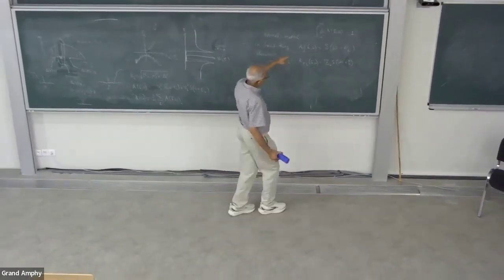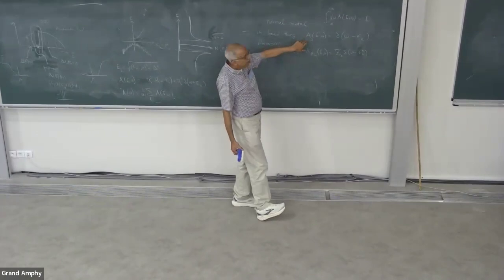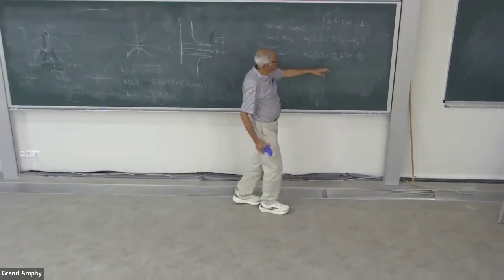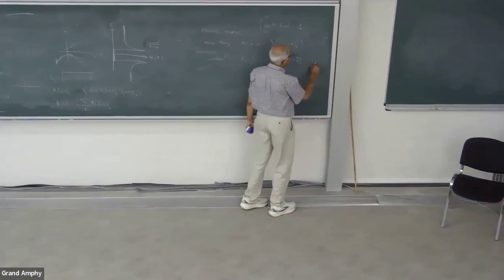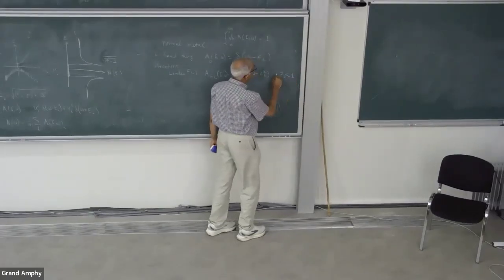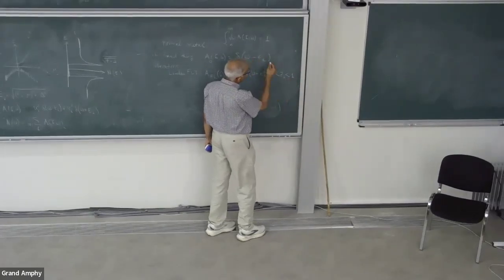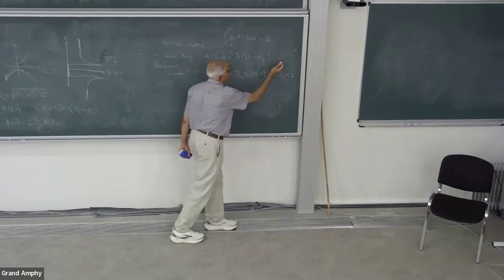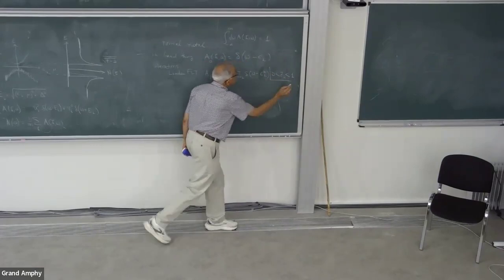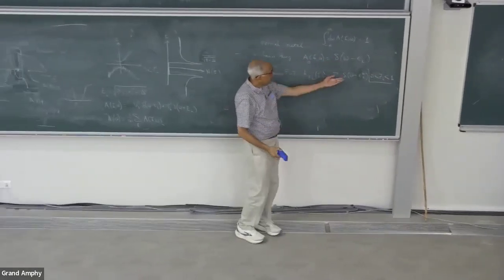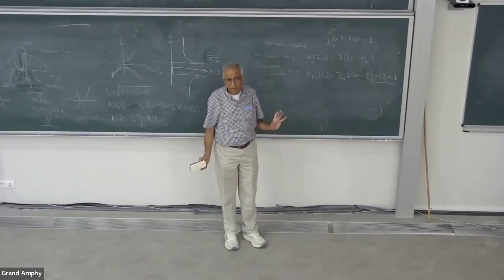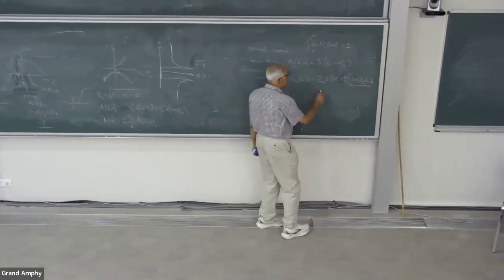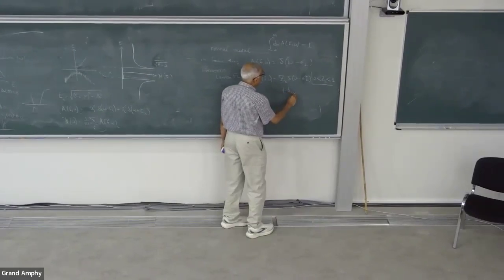So this is of course satisfied here. It's not satisfied here because I'm telling you that Z_k is strictly less than 1, and it could be 1, but then it would be a Fermi gas, but it has to be strictly greater than 0. In Landau Fermi liquid, the weight is Z, which is not 1. So there must be some incoherent piece.